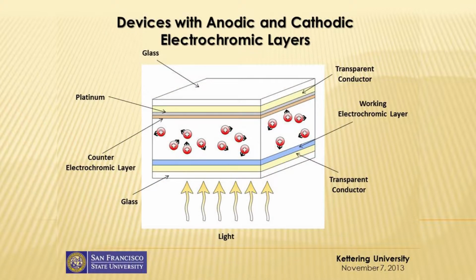That's the device with anodic and cathodic complementary electrochromic layers. The top is glass coated with transparent conducting layers. Also, the lower part is glass coated with a counter electrochromic layer. We use a very, very thin metallic layer, generally silver or platinum. Very thin is like 50 angstrom, the thickness is almost nothing.